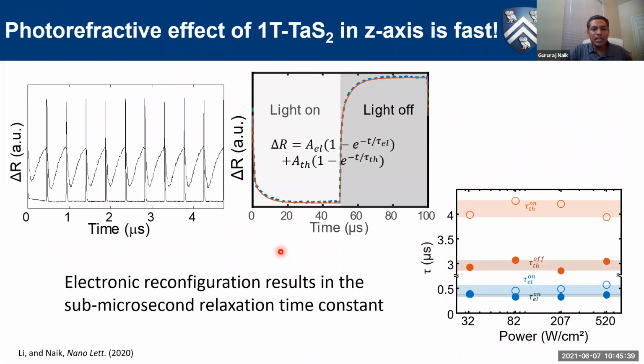Maybe we thought there is something to do with the stability of the material. Maybe it's reacting or something is happening. So we did even stability studies, etc. It was really stable. We could do all these measurements in just ambient air, and even after 3-4 days, this material was totally fine. We didn't see any degradation.